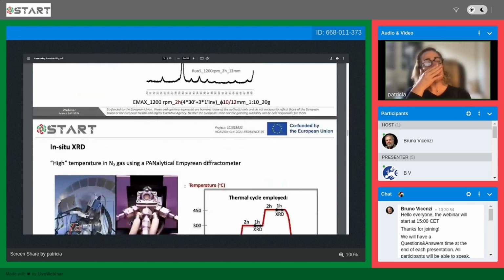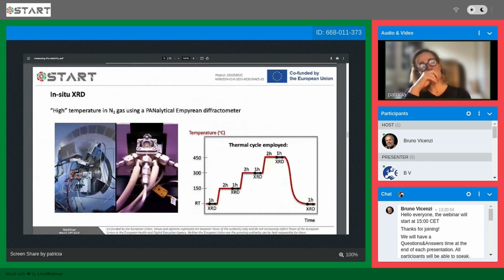Then one thing that we tried to do to characterize our material in terms of stability was to use in situ XRD. So you just do XRD while you're heating your material. And so this was the thermal cycle employed. So we started at room temperature, then we increased the temperature quite fast, we let it stabilize for 2 hours, and then we acquire another diffraction pattern, and so on.